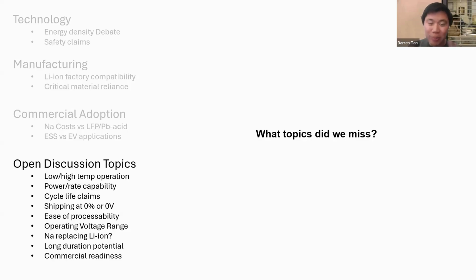But most companies don't ship it at 0% because it's inconvenient, right? They like to ship it at 2% or 5% because when the customer receives it, they do a quick quality check. And if their voltages are all in the same range, they accept it. And if one is out of this range, there's a poor quality request for warranty and stuff like that. But when you ship batteries at 0%, the range is very large, right? Because of the double layer capacitance in all the electrodes. So just simply out of convenience, most sodium-ion companies ship it at some amount of charge that's low enough. Yeah, but don't do 0 volt, at least until new knowledge is discovered.